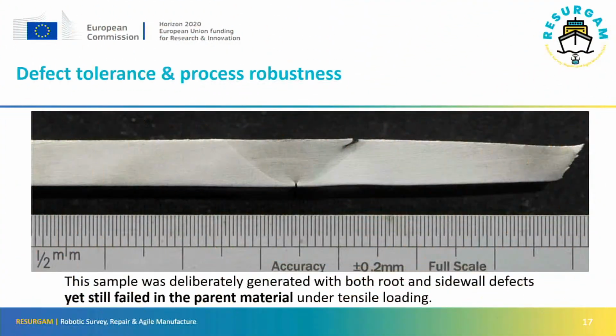So we made some welds that had deliberate defects in them. This is a 6 millimeter thick plate, so we welded it with a tool designed for welding 5 millimeter thick material. So we were left with a 1 millimeter unbonded region at the root, which is effectively a crack. We also rotated the tool far too quickly, so the softened steel didn't have time to flow the whole way around it and consolidate against the sidewall. And that gave us a second defect at the top of the weld. Again, just over 1 millimeter in size.